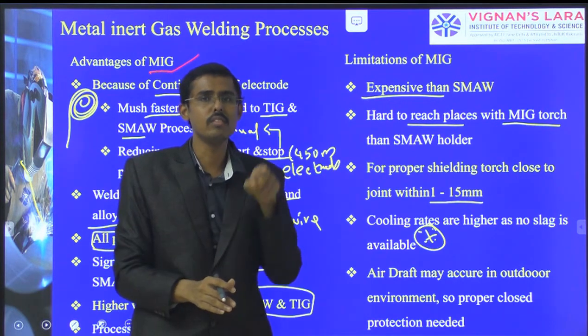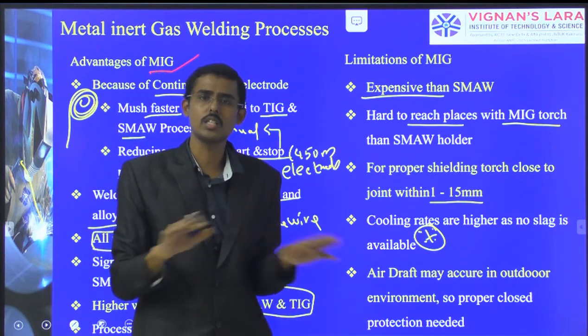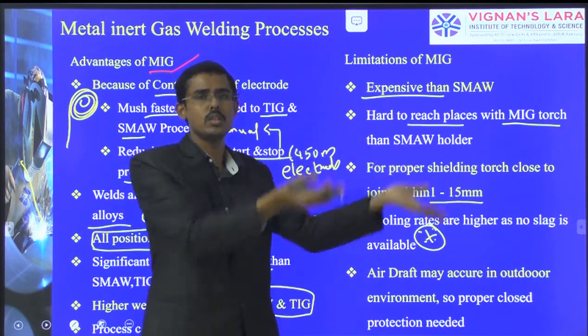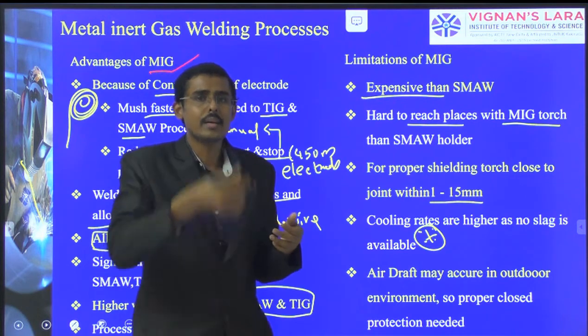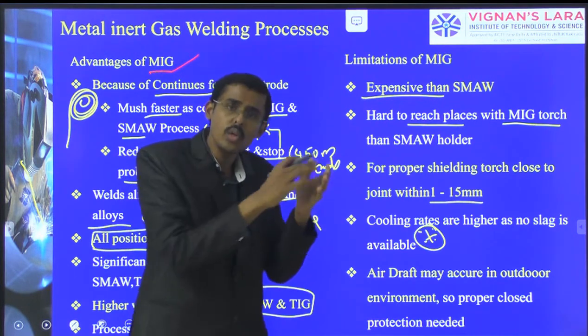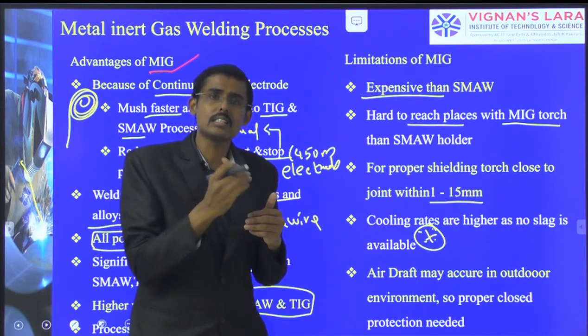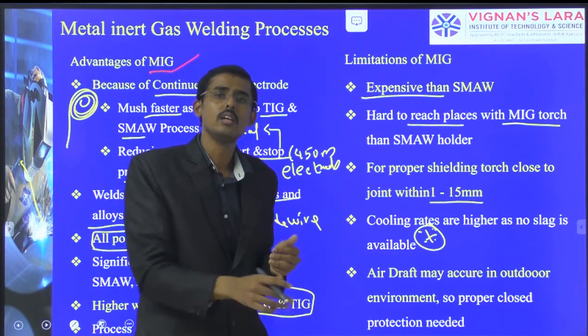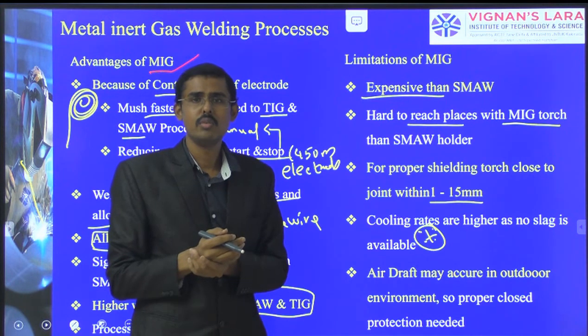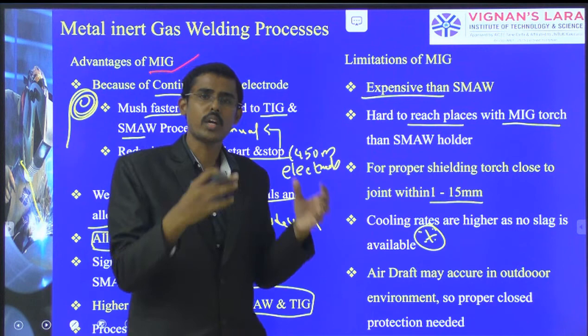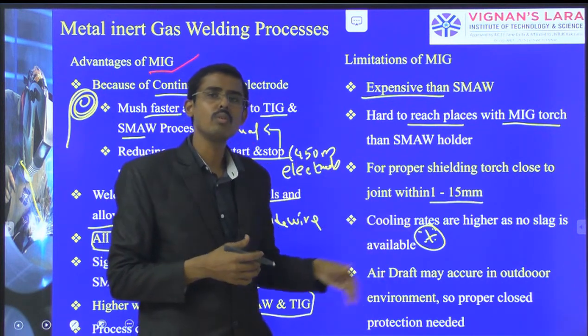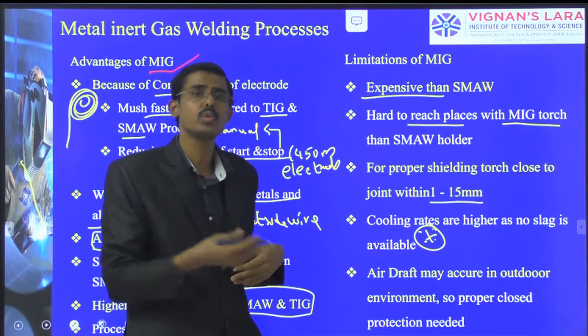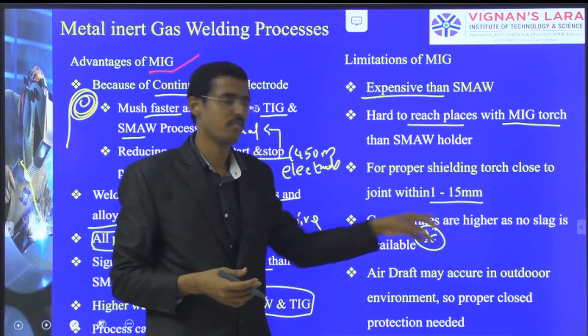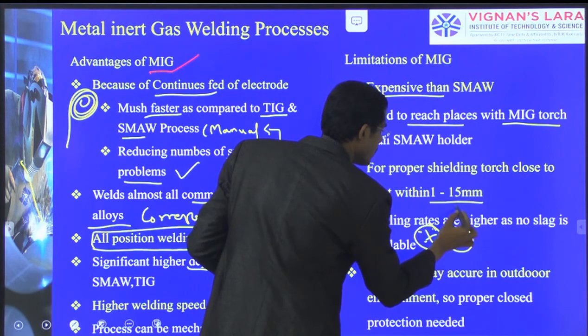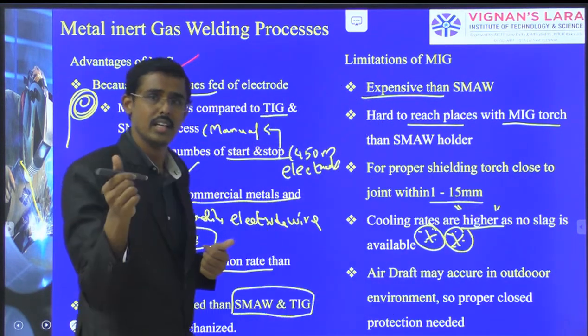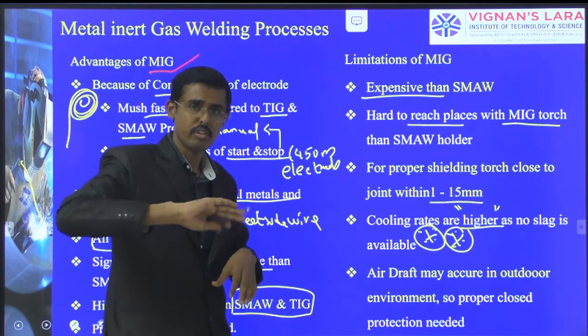Until welding is completed, we are giving the shielding, protecting from atmospheric contamination. When the welding is completed, we remove the shielding and the weld is exposed to the atmosphere. Therefore, due to the temperature gradient, the cooling rate will be faster. If the cooling rate is faster, there are chances of martensite and brittleness in the alloying systems or metals. We may not achieve the ductile property of the material. So some protection has to be given from the atmosphere during cool down, or after this MIG welding process we have to go for heat treatment to improve the properties of the metals. Very important point: the cooling rate is higher here. But in SMAW and submerged arc welding, the cooling rate is slow because the flux protection is there.